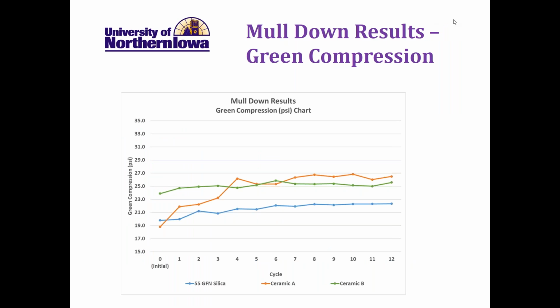We also, because this was a test for green sand applicability, did what was called a mull down test. What we do in this is we mull bentonite, sea coal, and water with sands, and then we measure the initial properties after 5 minutes of mulling in a 2-wheel or vertical wheel muller. And then we measure the properties every minute out to 12 minutes.